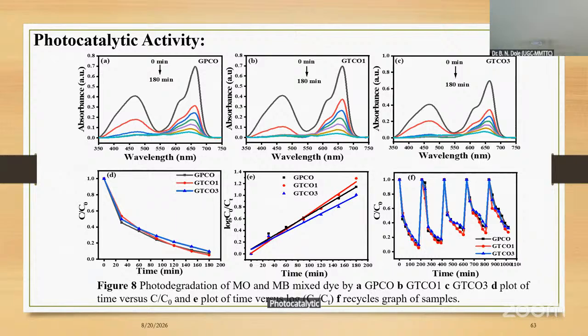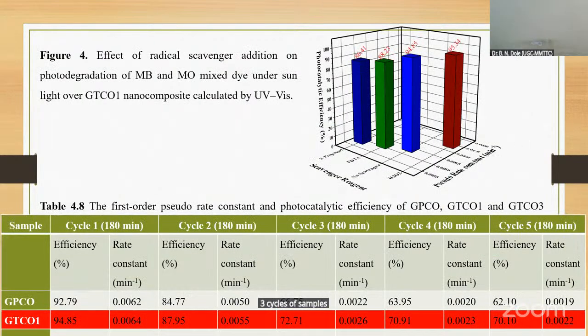Photocatalytic activity. Now this is the photodegradation of MO, methyl orange, and methylene blue mixed dye by these. And now this is the plot of time versus log. Recycles graph of samples. Effect of radical scavenger addition on photodegradation of MB and MO mixed dye under sunlight over GTCO1 nanocomposite calculated by UV-Vis. The first order pseudo rate constant of photocatalytic efficiency of GPCO, GTCO1 and GTCO3 samples.